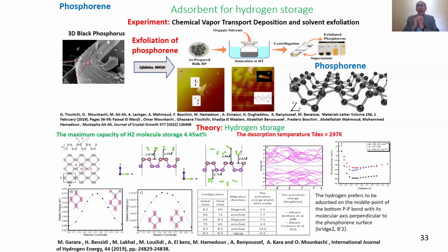Here is how this has been done using density functional theory. The first step is to look for the most stable position for the hydrogen molecule: on the top of the phosphorus, or on the hollow, or on the bridge. And it has been shown that the hydrogen prefers to be adsorbed on the middle point of the phosphorus-phosphorus bond, with the molecular axis perpendicular to the phosphorus.